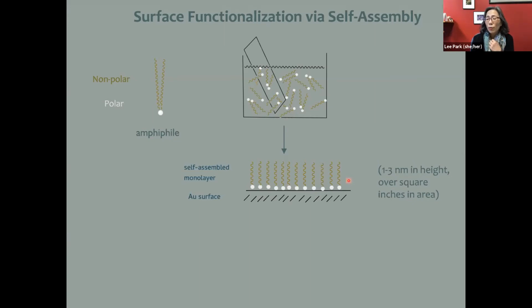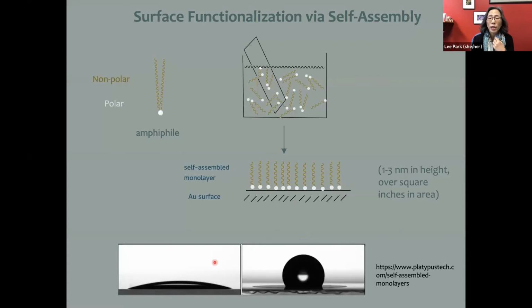But here's the thing, what you've put on the surface is a molecular monolayer. This layer is exactly one molecule thick. And so when you pull your slide out of the liquid, you can't tell that you've done anything. You can't see that. So how do you convince yourself that something's actually happened? What we can do is take a surface and put a water drop on that surface. And if you have a surface that is hydrophilic, then as I talked to you about on the previous slide, the water drop is going to be happy to interact with that surface, and it's going to spread out, and it might have a profile that looks like this.